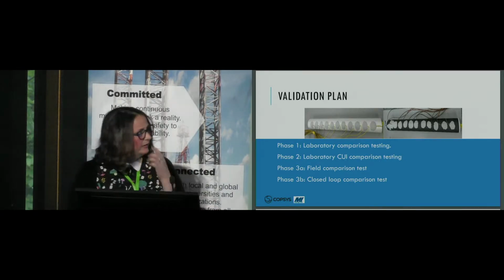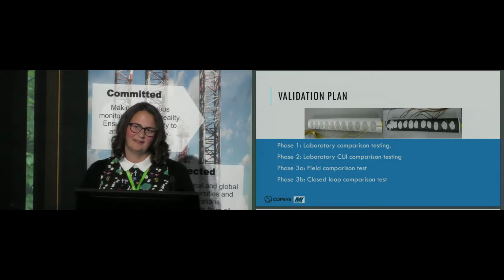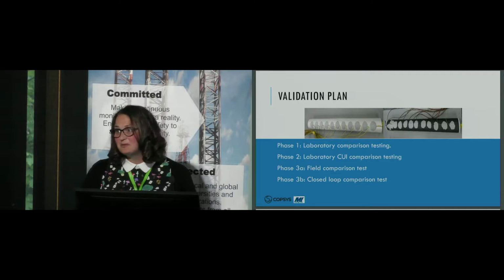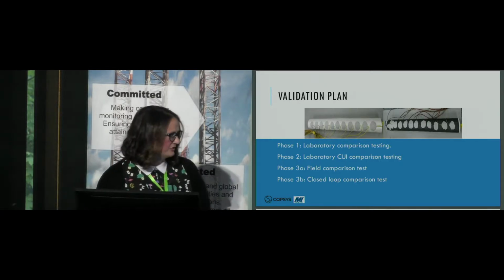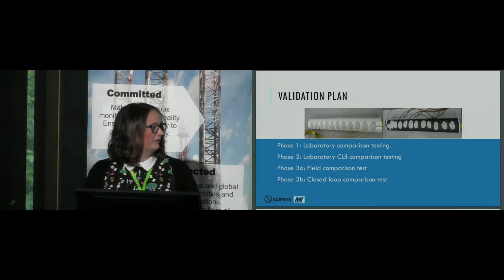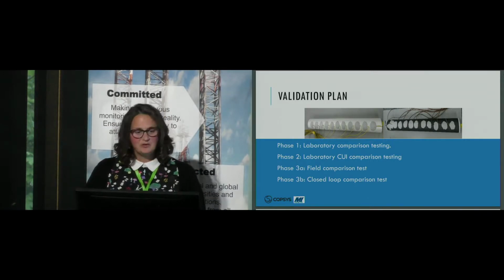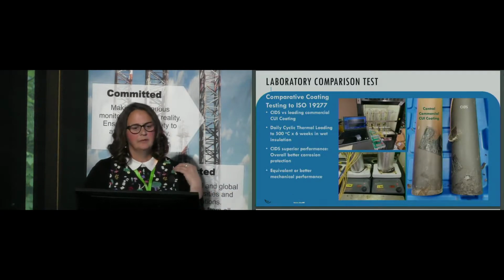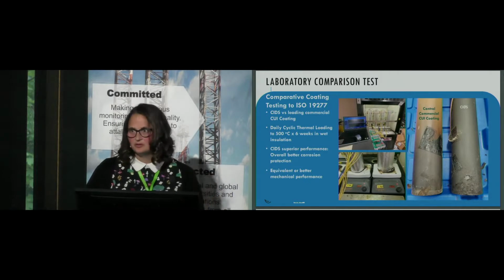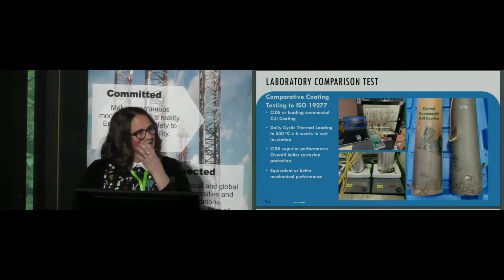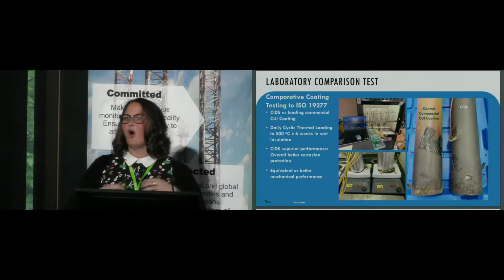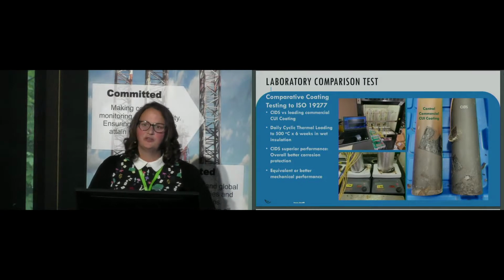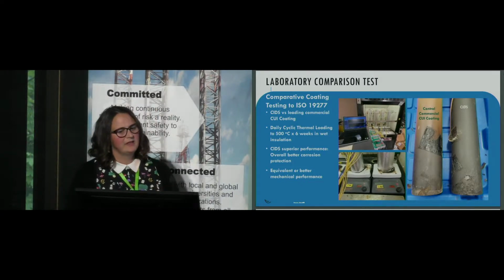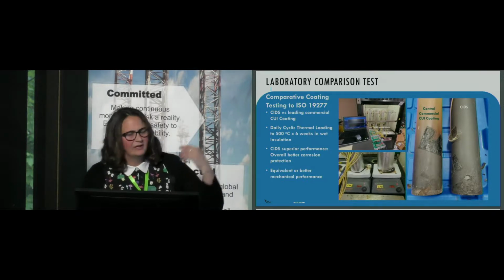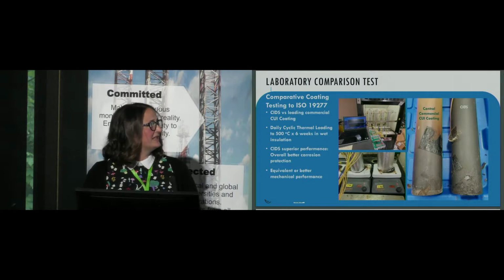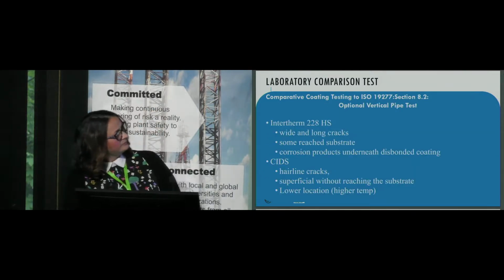But what we're working on here, as I talked about with the project that Charles helped with, is that we have some experience with field testing and laboratory testing for corrosion under insulation. And that's what phase 2 and phase 3A are. In phase 1, we compared a typical commercial coating to the CIDS coating, not only for mechanical properties, to make sure it did all the jobs any coating would do, but also for better corrosion protection. We started off with ISO 19277, the optional vertical pipe test.